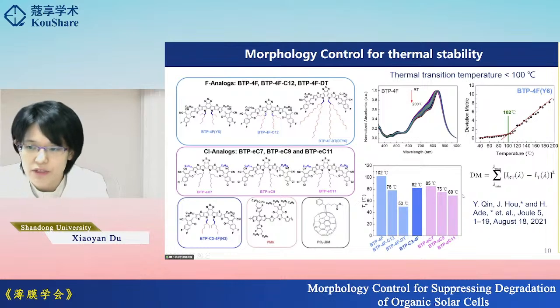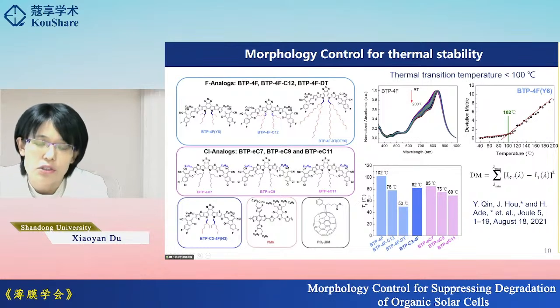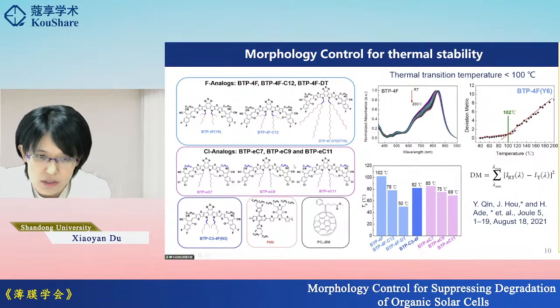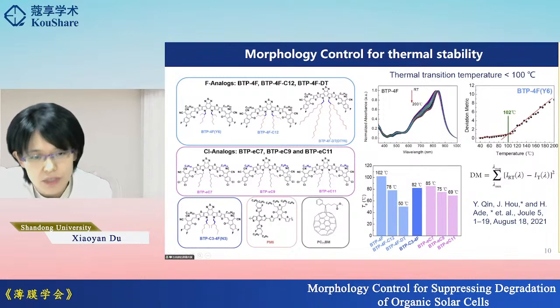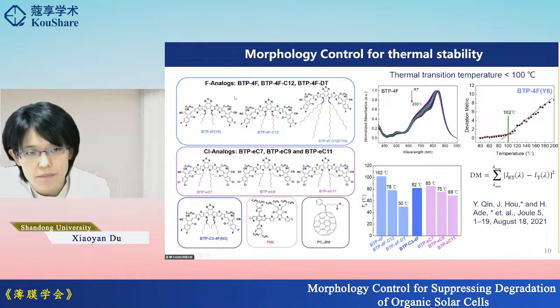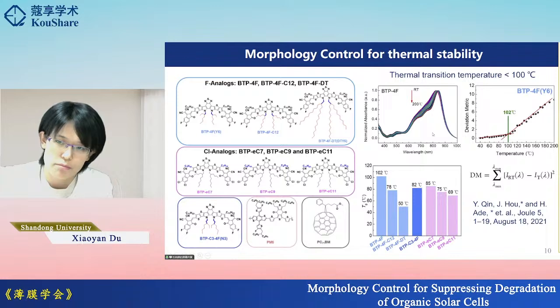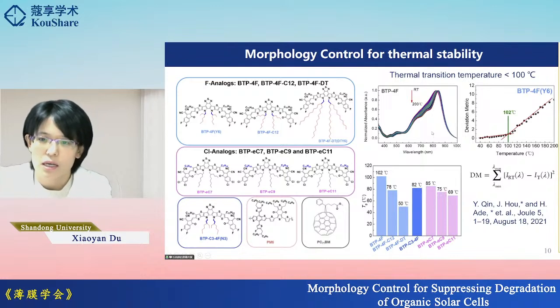Tg, in this work, Professor Hou and Professor Ade investigated the thermal transition temperature of a series of high-performance non-fullerene acceptors based on this BTP and its derivatives. Here, the Tg is measured by the deviation in the absorption spectra upon heating or annealing of the thin films. This is a very sensitive method to measure the thermal transitions in thin films.